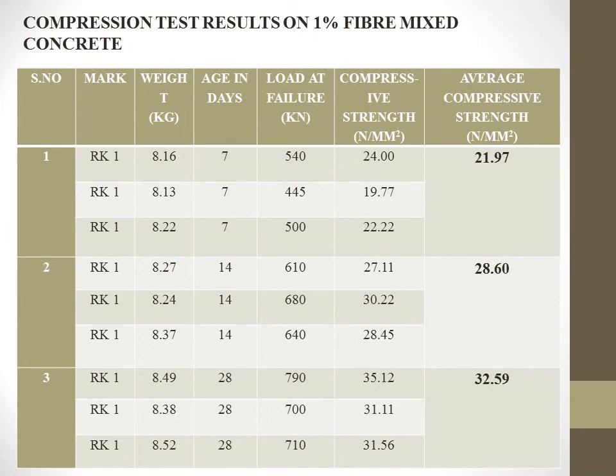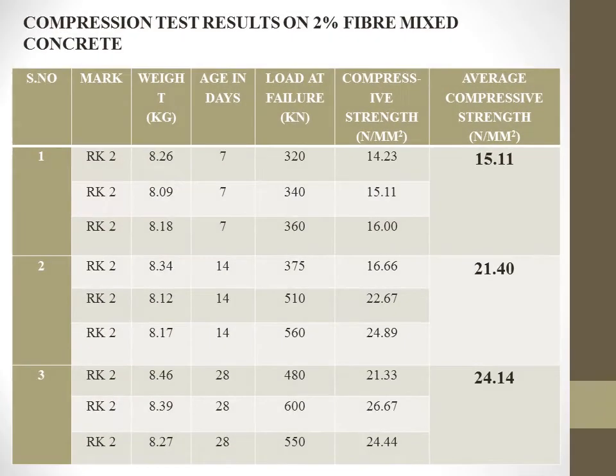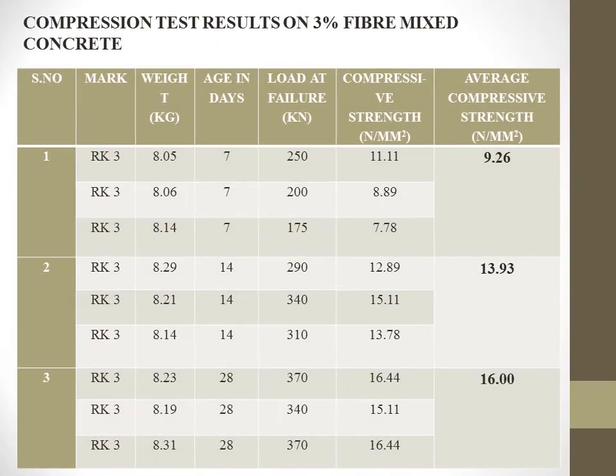This is the tabulation results with 1% fiber mixed concrete. That is, we had mixed 1% of the cement content as bamboo fibers in the concrete mix, and after 28 days of curing, the strength was found to be approximately 33, which is higher than the previous result. And this is the compression test results on 3% fiber mixed concrete, and the value has decreased after 28 days of curing to 16 Newton per mm square.